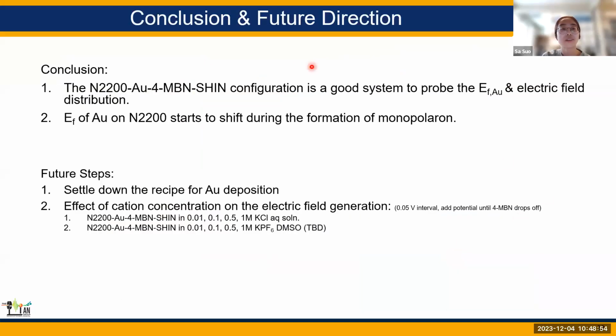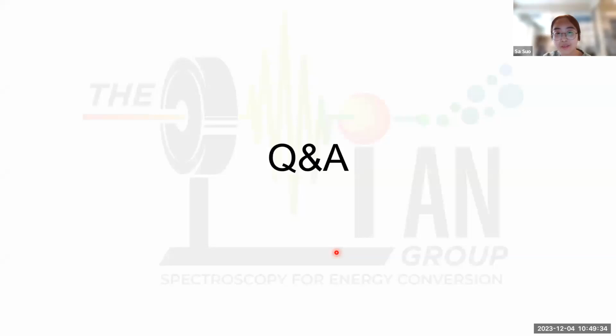So in conclusion, I think the N2200 deposited with gold and functionalized with 4-MBN-SHIN should be a good system to probe the gold Fermi level and further mimic the platinum catalyst electron transfer mechanism. And our big finding is that the Fermi level of gold on N2200 will start to shift during the formation of monopolaron. We will continue doing this experiment in a more rigorous way, for example, studying the cation concentration effect on the electric field generation. Thanks for listening, and I'm happy to take any questions.